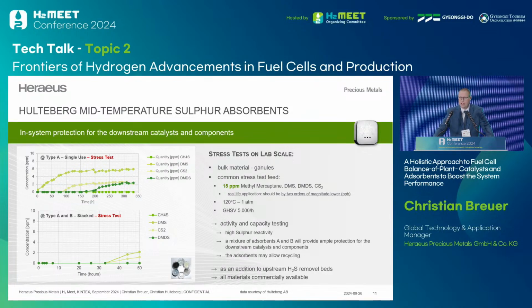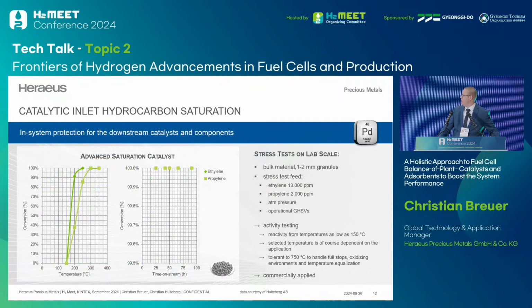Now, considering that the actual concentrations are between 100 and 1,000 times lower than the conditions of the stress test, we can basically show that with these materials we can buy the system some further time to protect it from sulfur poisoning. And then downstream of that, we have the saturation catalysts.